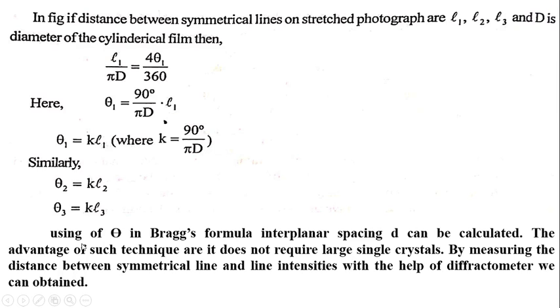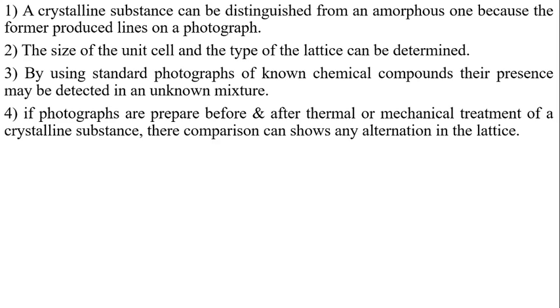Using theta in Bragg's formula, the interplanar spacing d can be calculated. The advantages of this technique are: it does not require a large single crystal; by measuring the distance between symmetrical lines and line intensities with the help of a diffractometer we can obtain results; a crystalline substance can be distinguished from an amorphous one because the former produces lines on the photograph.